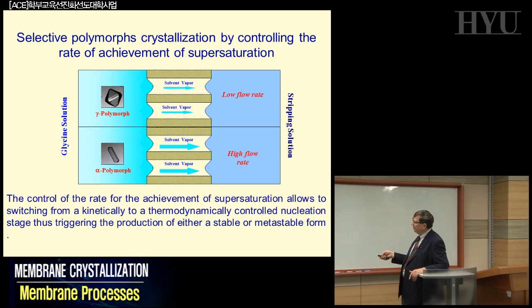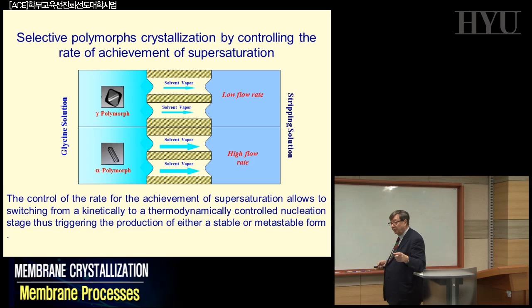You can start to see here that these two forms are very different also in terms of the final geometry, and you can have an idea that in some low flow rate was giving this form, and high flow rate is this other one. So there is an effect of the velocity on the membrane surface that can orient, that can facilitate in this probabilistic interaction one form or the other.